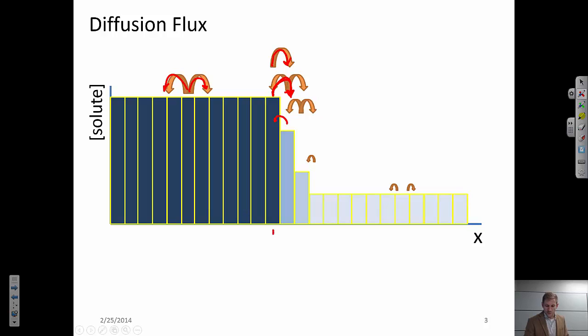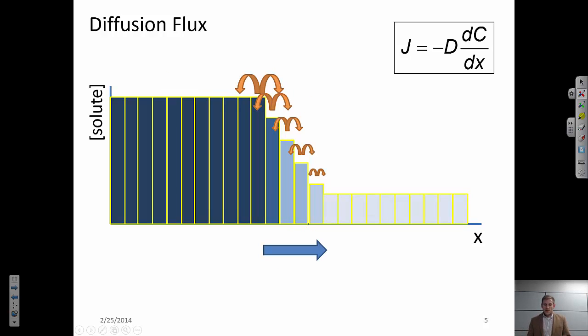And so we could do this experiment again and again. We have a large flux from bin 1 to bin 2, we have a moderate flux from 2 to 3, maybe a smaller one from 3 to 4. But in each case, the flux in one direction from left to right is larger than the flux from the right to the left. And so what we end up getting is a case where we can measure what is the flux over some finite thickness. And for the exact reasons that we just described, this flux, which I describe by the letter J, is going to equal the mass per unit area per unit time. So this would be a mass flux.